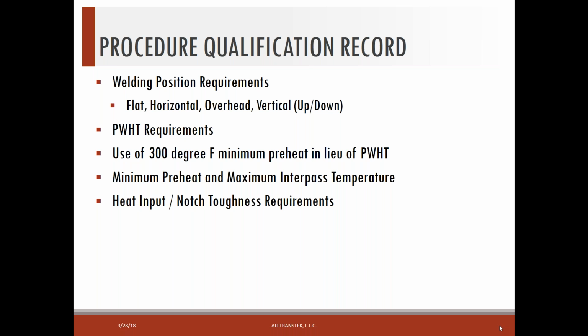Post-weld heat treat obviously is an essential variable. We have to qualify a procedure. If we don't use post-weld heat treat, if the procedure is used in the as-welded condition, and we add post-weld heat treat, it has to be qualified with that post-weld heat treat. Now in Appendix R and also Appendix W, we have an option to use a 300-degree minimum preheat in some cases in lieu of post-weld heat treat, and that's mostly for repair of tank cars, as specified in paragraph R24, I believe, of Appendix R. So this is not for pressure cars, but in some cases on GP cars, we can use the 300-degree preheat in lieu of post-weld heat treat. However, we have to control our preheat or qualify the procedure with that preheat.